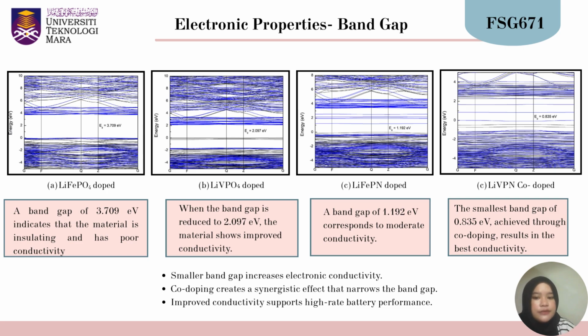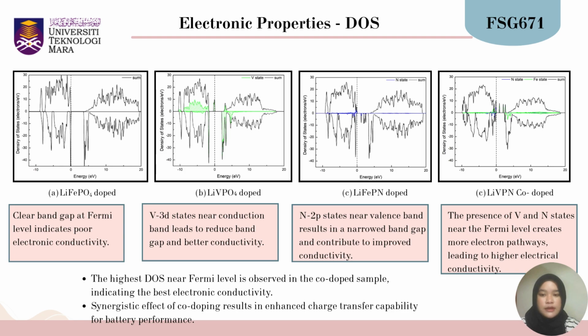The best result is from the co-doping with vanadium and nitrogen, which gives a band gap of 0.835 eV. This is the lowest value, meaning the highest conductivity. This shows that co-doping is more effective than using either vanadium or nitrogen alone. In addition to the band gap, I also looked at the density of states, DOS, to understand how doping affects the conductivity. For the pure LiFePO4, the DOS shows a clear gap at the Fermi level, meaning there are no available electrons to conduct electricity. So it confirms that it has poor conductivity.